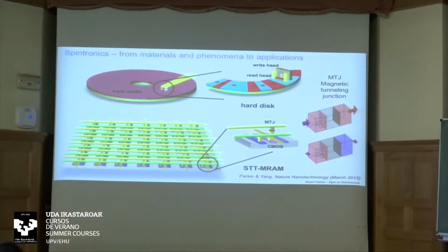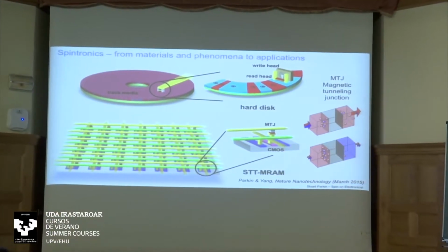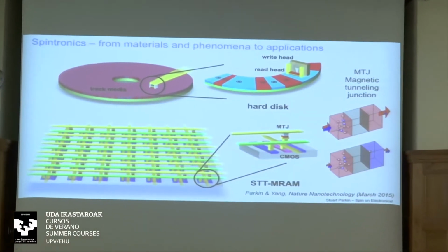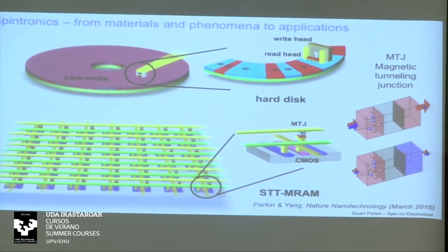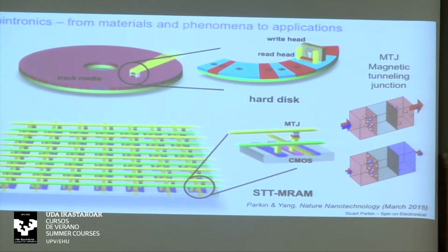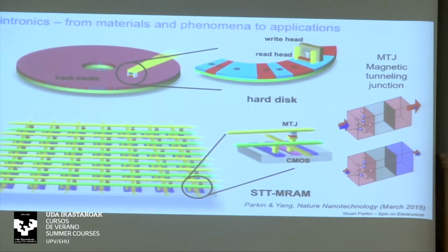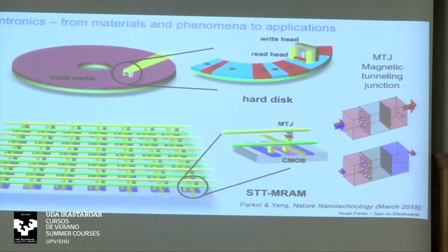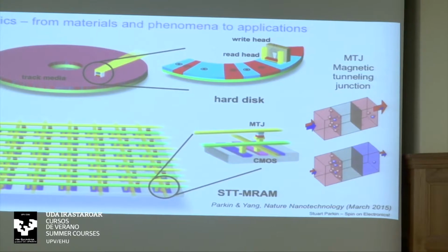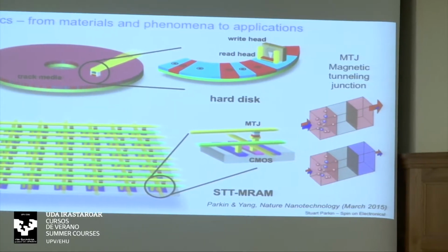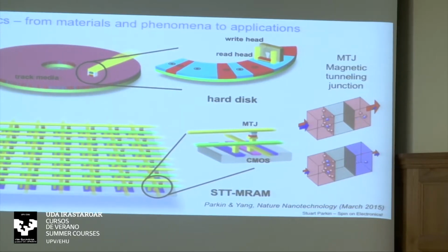And the tunneling current that flows is innately spin polarized because of the spin-dependent density of states in the magnetic electrodes. But in addition, the tunneling junction itself can filter out electrons of one spin orientation if up and down spin electrons have different symmetries in their wave functions. And then the penetration depths of the wave functions through the tunneling barrier can be dependent on the spin.